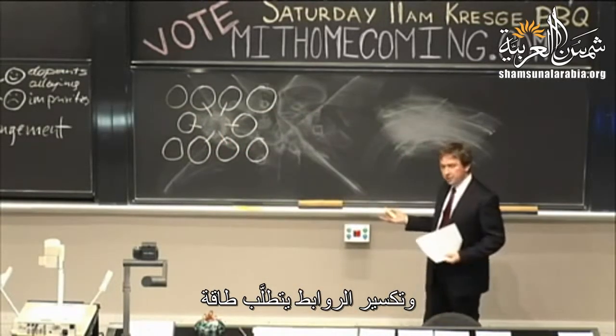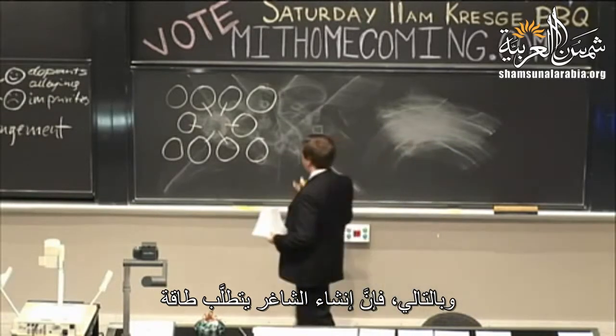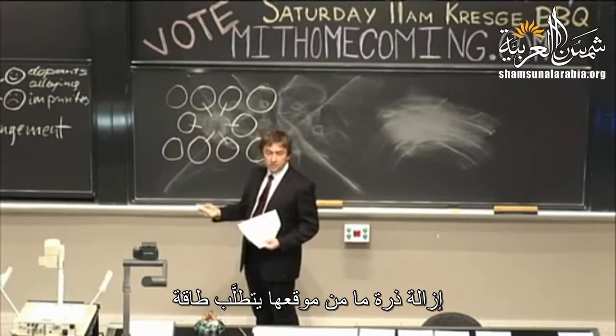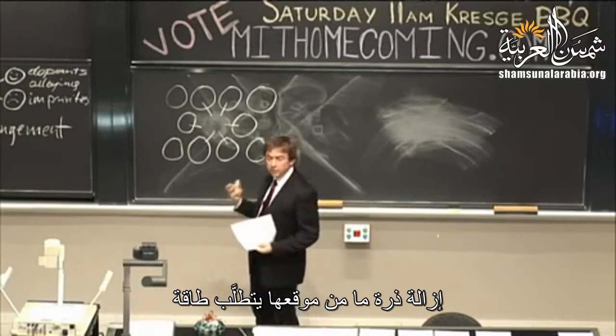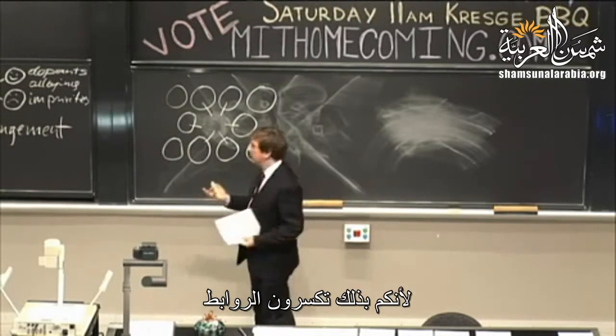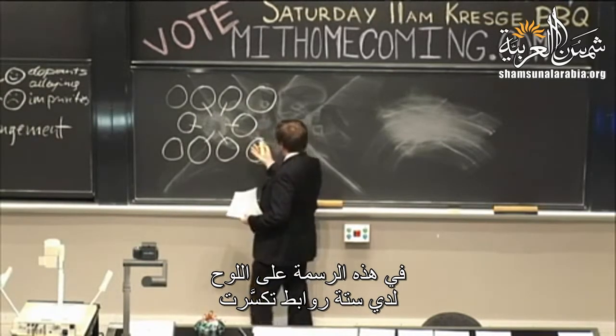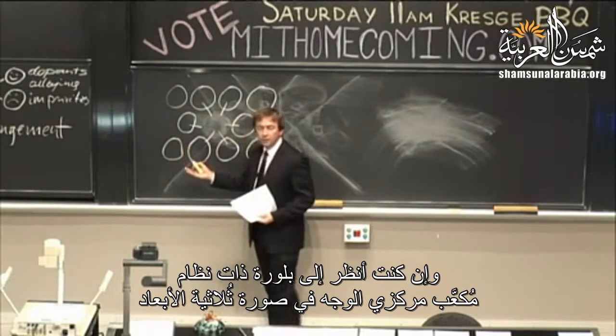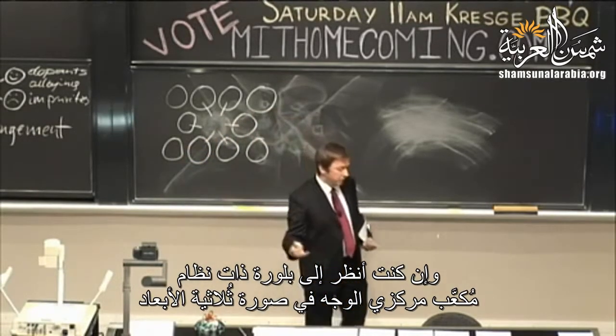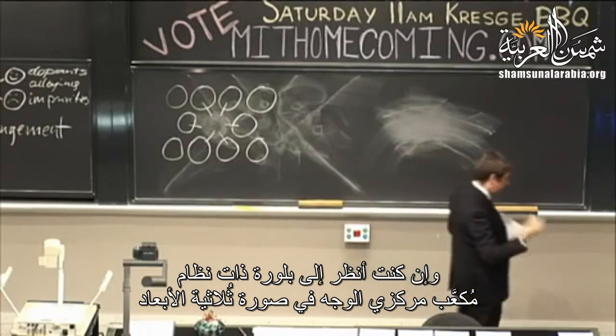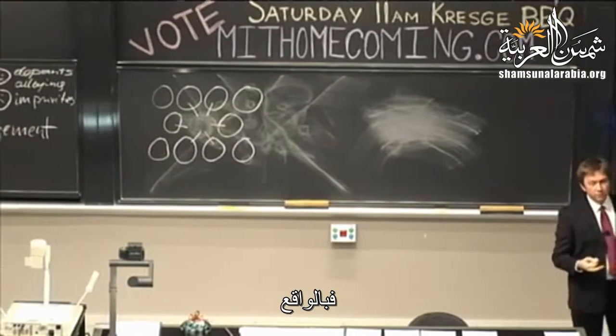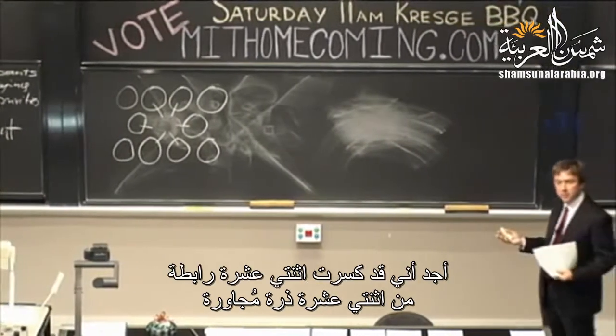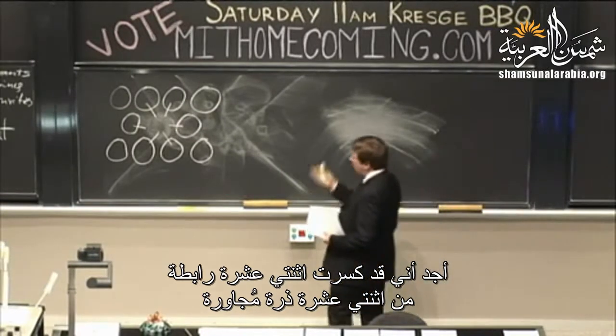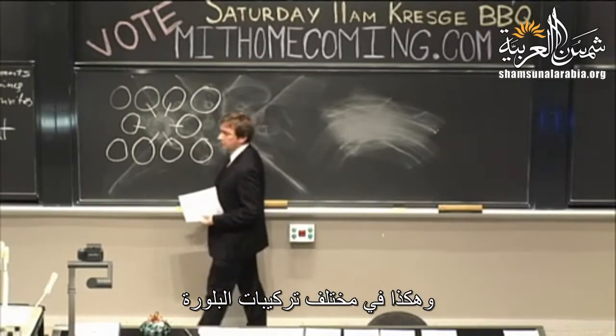Breaking bonds costs energy, right? So it costs energy to create a vacancy. It costs energy to remove an atom from the place where it would have been because you're breaking bonds. So in this case, I have 6 bonds that I broke. If I were looking at some material, for example, a face-centered cubic material in 3D, I would find that I would be breaking 12 bonds, right, to the 12 nearest neighbors, and so on for all the different crystal structures.